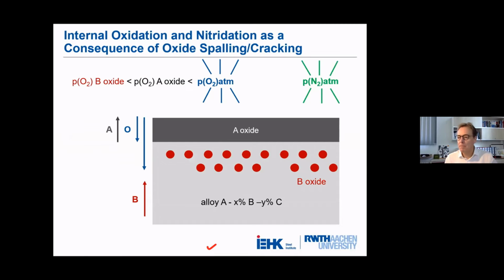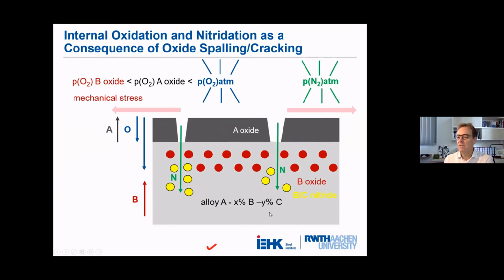Well, if you go back to the schematics, then we have the situation: we have the A oxide and internal oxidation of B oxide, but at the same time we have a high nitrogen partial pressure. That is a situation that we just have in air. If a mechanical load is then superimposed, the oxide may crack, and there is access for the nitrogen, and then there's a risk of deep internal nitridation attack.